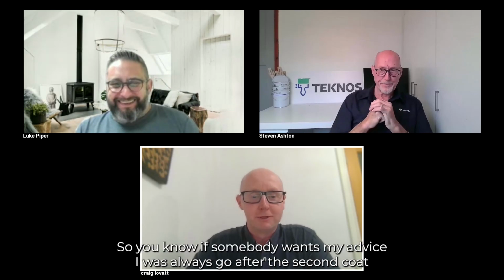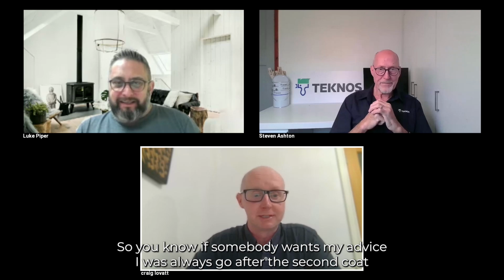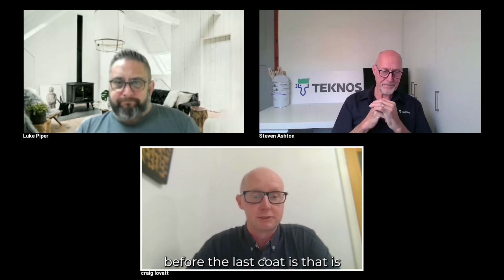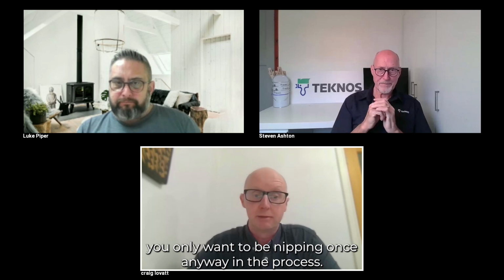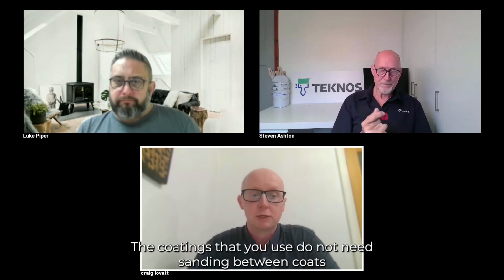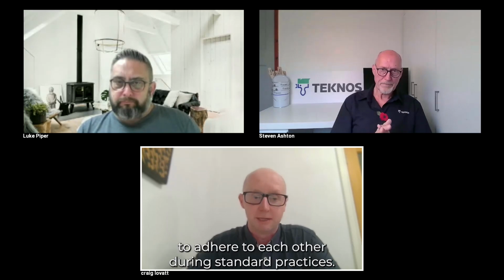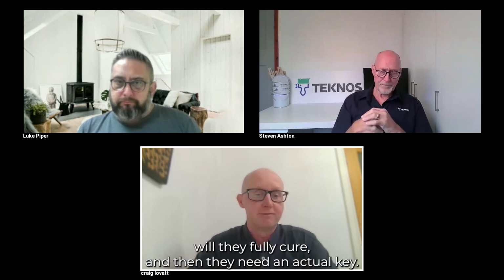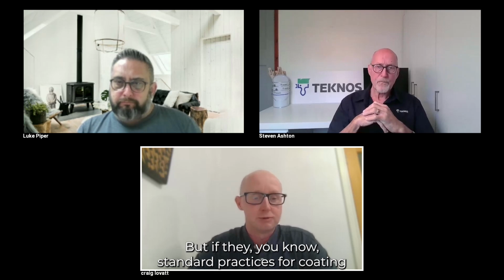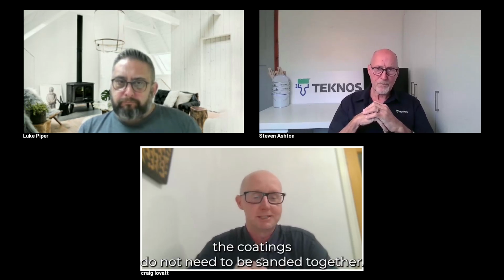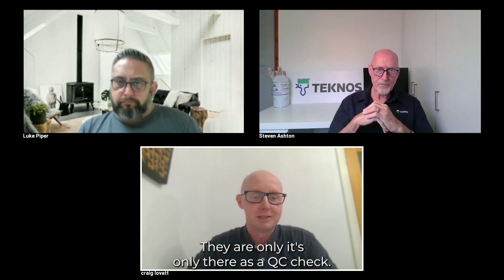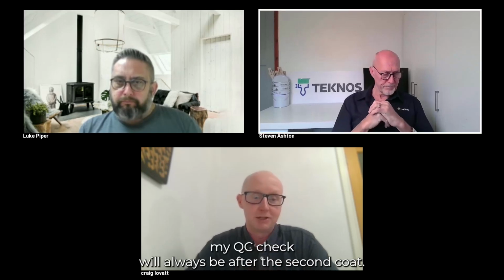I'm always one for, if somebody wants my advice, I always go after the second coat before the last coat, because you only want to be denibbing once anyway in the process. The coatings that you use do not need sanding between coats to adhere to each other during standard practices. Only if you've left them for a period of time will they fully cure, and then they need an actual key. But in standard practices for coating, the coatings do not need to be sanded together. It's only there as a QC check. So my QC check would always be after the second coat.